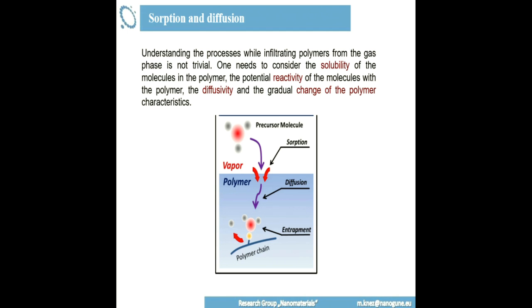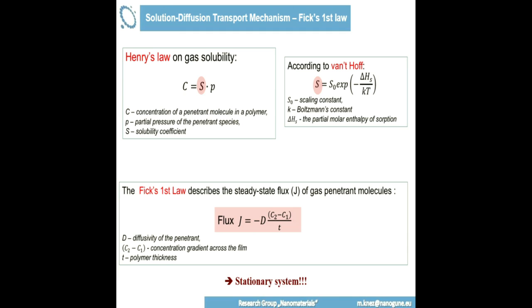At the end, basically, you start thinking about this situation. You have a precursor, it comes to the surface of the polymer, it's absorbed, it diffuses, and if the polymer allows this situation in terms of chemistry, then the precursor will bind to these functional sites of the polymer, and you will have a material inside, trapped inside of the polymer, that means in the subsurface area. Now you have to consider several points here in terms of building up a theory around it. You have Henry's law, which you can put in here. You have van 't Hoff's relation, which you can insert here. But the Henry's law you can put into Fick's equation and so on. So I will not go into detail here. This is not really that important. You can really look it up in Mark's paper.